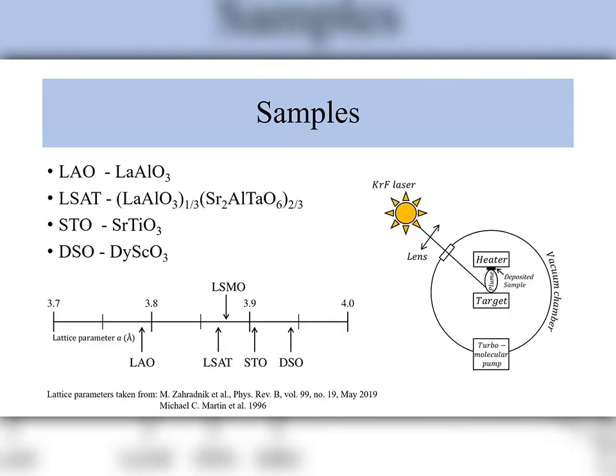In order to investigate the effects of epitaxial strain, we have prepared four samples of thin film LSMO of approximately 25 nm by pulsed laser deposition. The four samples are deposited on four substrates with varying degrees of epitaxial strain, ranging from high compressive on lanthanum aluminate, to low compressive on lanthanum aluminum strontium aluminum tantalate, to low tensile on strontium titanate, all the way to high tensile strain on dysprosium scandate.